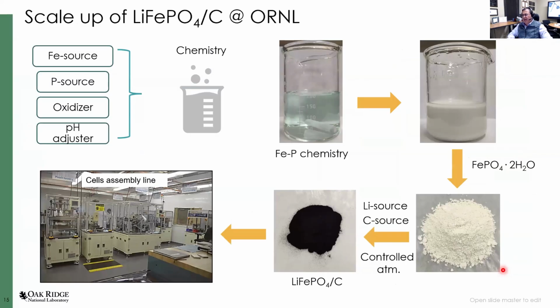Here at Oak Ridge National Lab, we developed a proprietary process based more or less on similar raw materials. We use iron, phosphorus, and oxidizers, pH adjuster. This is mainly a heavily chemistry-dominated process. There is a lot of know-how. By just sharing some pictures here, you can see the Fe-P chemistry, how it works.